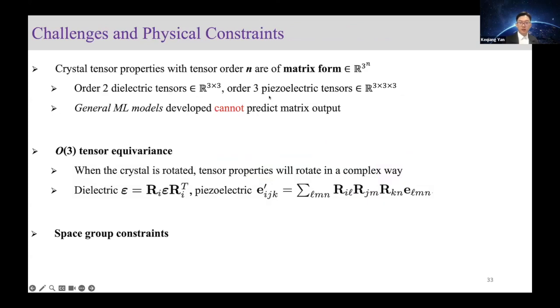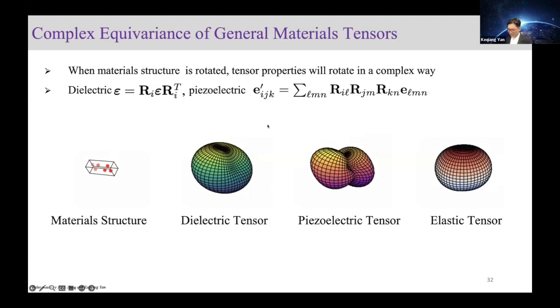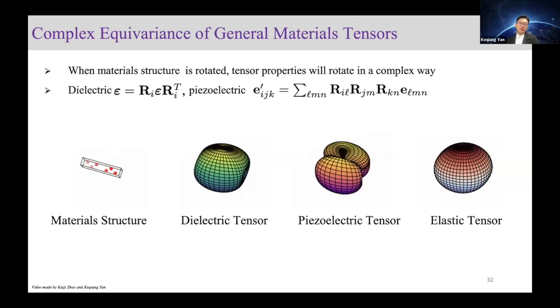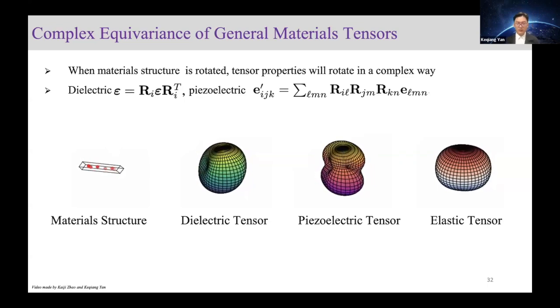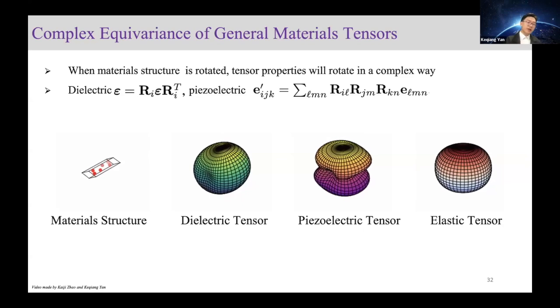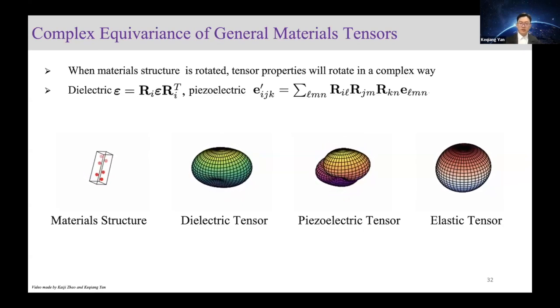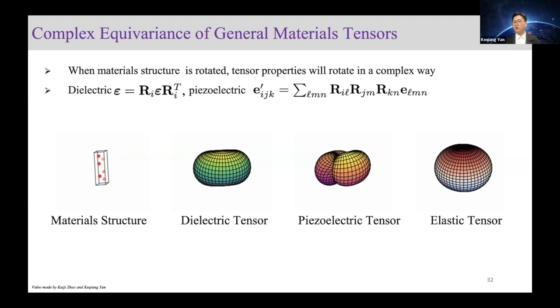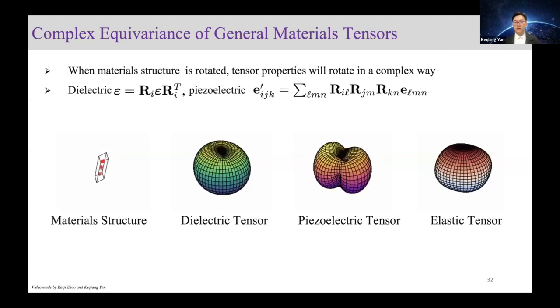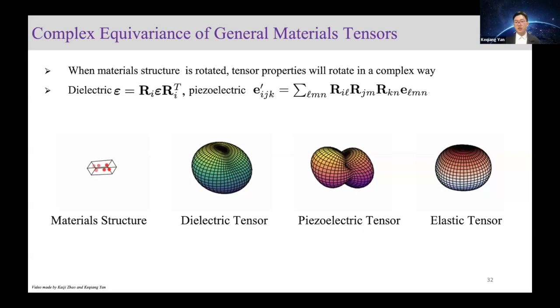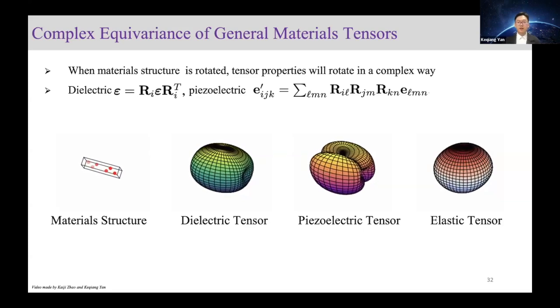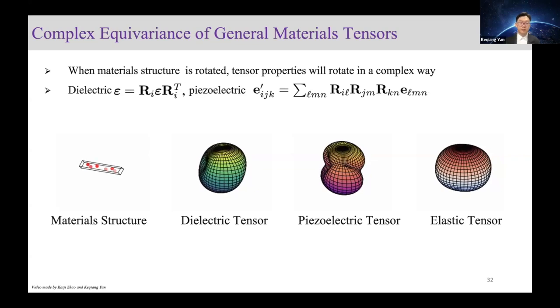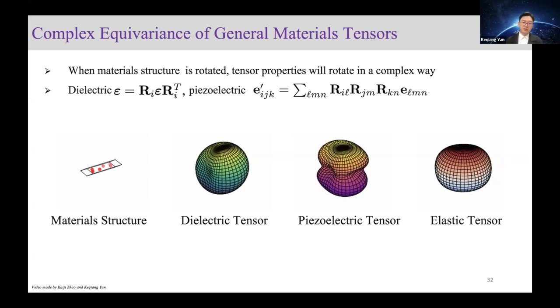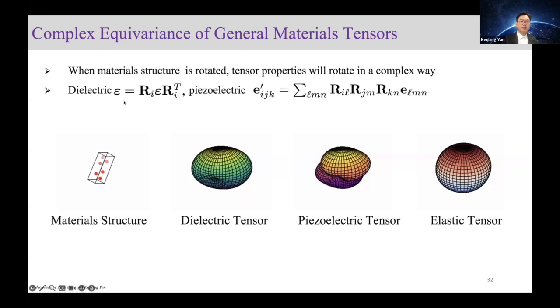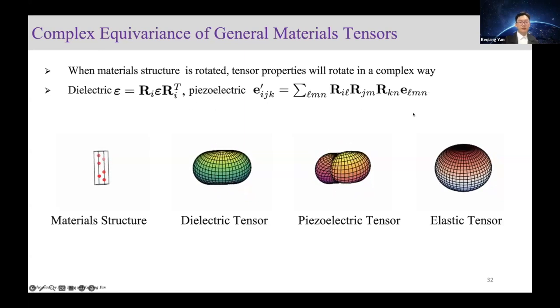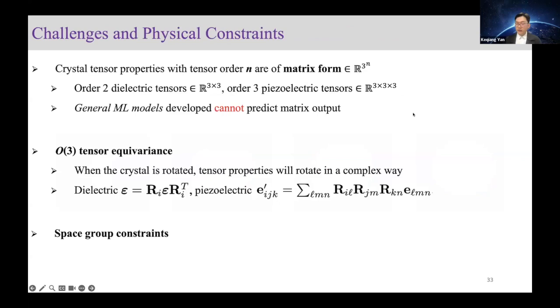The first major challenge for predicting tensors is equivariance. As I show here, if we rotate the material structure, the dielectric tensors and other high-order tensors will rotate in a complex way. Not only the direction, but also the shape will change. However, they actually have a rather simple mathematical relationship. If you rotate the structure by R, the dielectric tensor will rotate by this equation, and the piezoelectric tensor will rotate by this equation. And generally speaking,